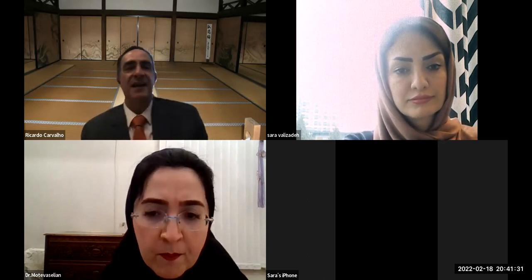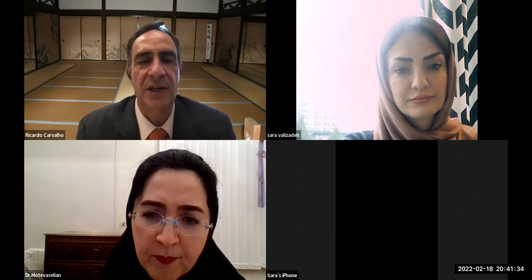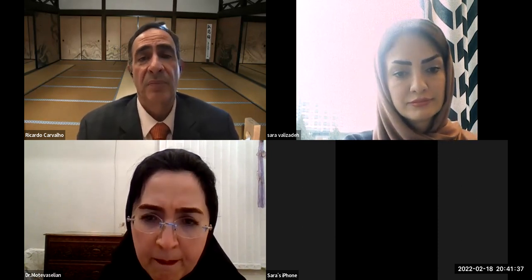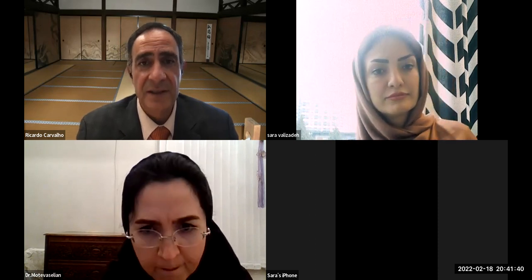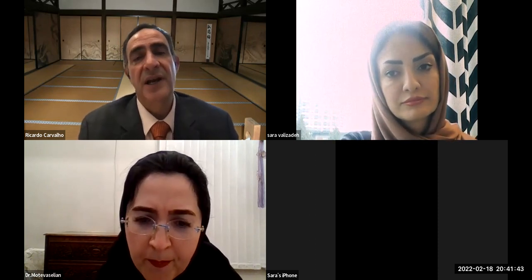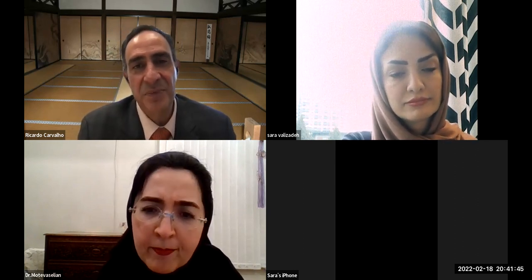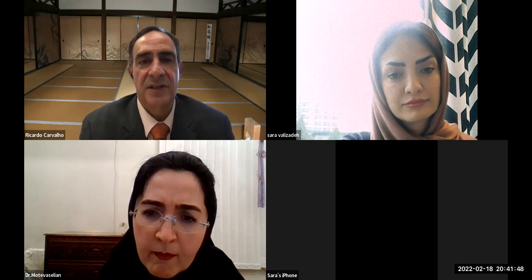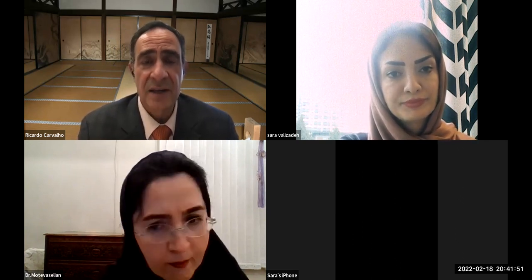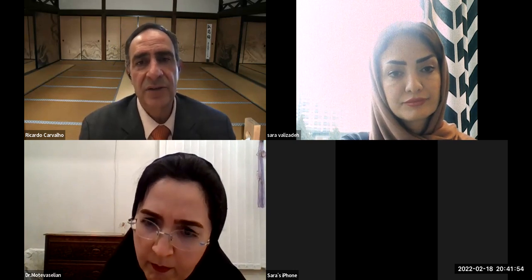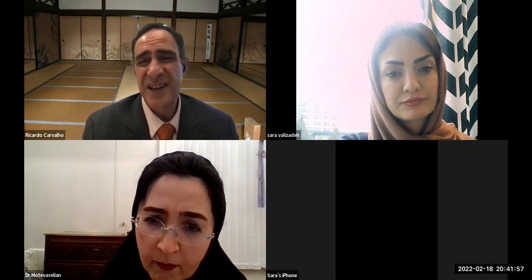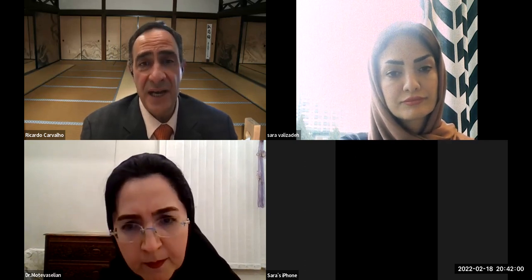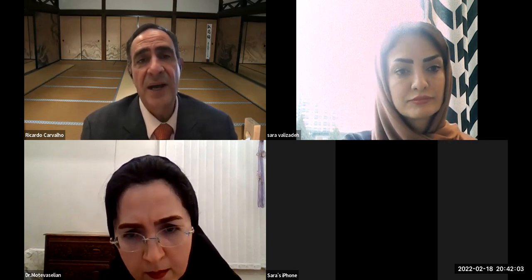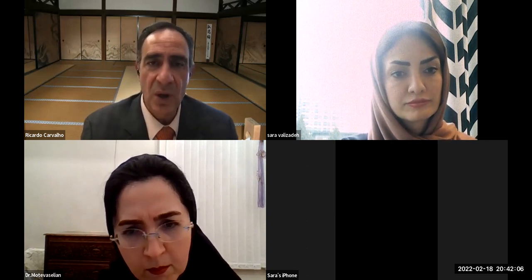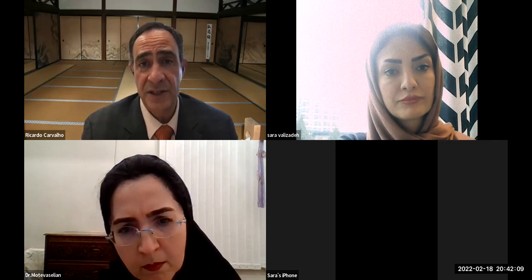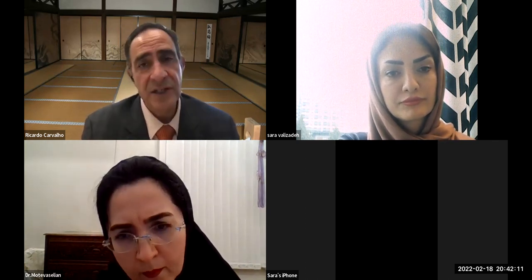Okay. Thank you. So ideally, try-in paste, you either apply and use before you etch, or you apply and use after you silanize. The reason is that before you etch, the surface is natural. There are porosities there. The try-in paste will eventually get into the porosities, but the surface is rather hydrophilic at this point because you didn't etch yet. So by rinsing the try-in paste with water, because most of the try-in pastes are water-based, right? So you have to rinse it well,